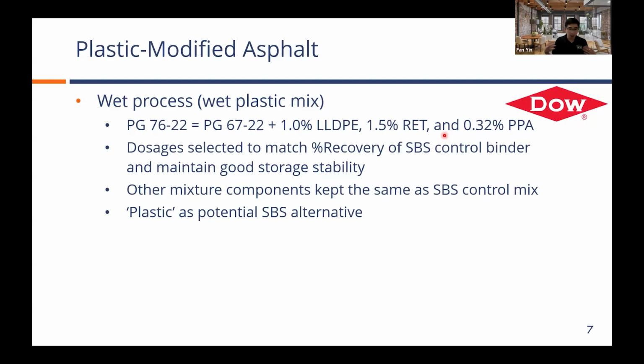And then all the other mixture components were kept the same. So the only difference from the SBS control mix was we switched the binder from the SBS binder to this hybrid polymer system using plastics. With that being said, this mix allows us to look into the potential of using plastic along with some other terpolymer system to behave as a potential SBS alternative.